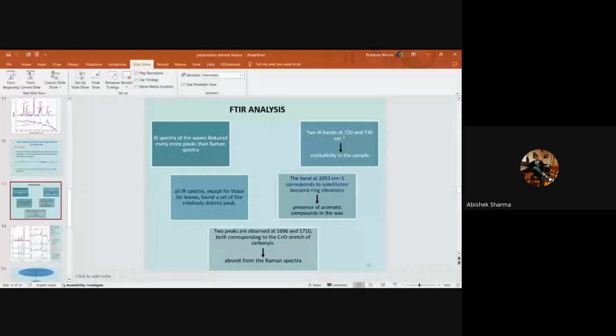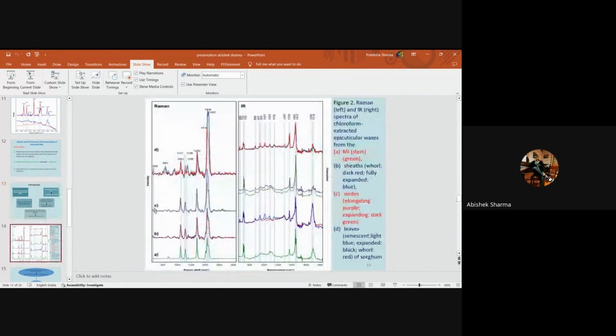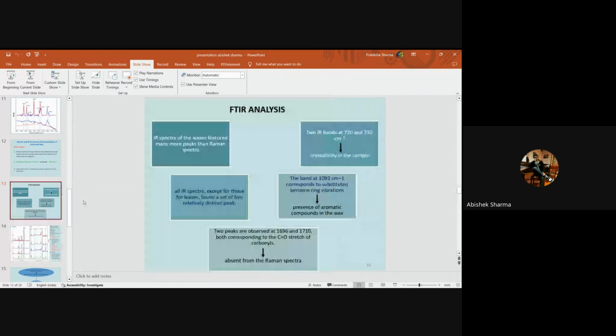These bands show that there is crystallinity in the sample. Okay. So in IR spectra, except for the leaves, they found a set of five relatively distinct peaks, and the band at 1093 centimeter inverse that corresponds to substituted benzene vibrations. So they found out that there are some aromatic compounds present in the wax. Then the two peaks at 1696 centimeter inverse and 1710 centimeter inverse, as we can see from the graph, showed that these peaks correspond to the ketonic stretch of carbonyls, which are absent in the Raman spectrum.